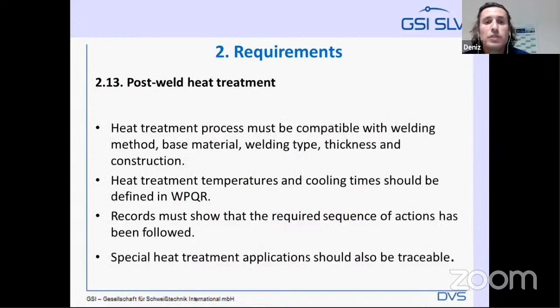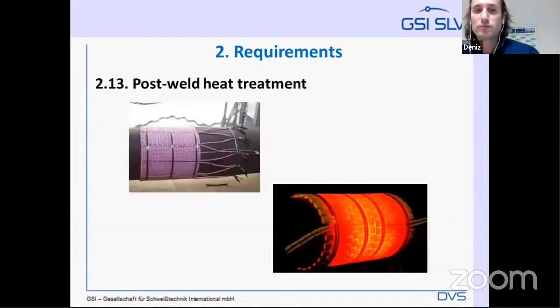And post-weld heat treatment. The heat treatment process must be compatible with welding method, base material, welding type, thickness, and construction. Heat treatment temperatures and cooling times should be defined in WPQR. Records must show that the required sequence of actions has been followed, and special heat treatment applications should also be traceable. An example, electrical resistance heat treatment method for welded steel.